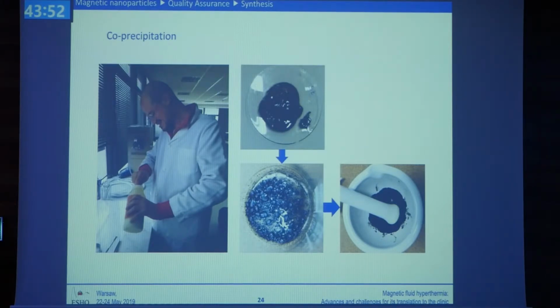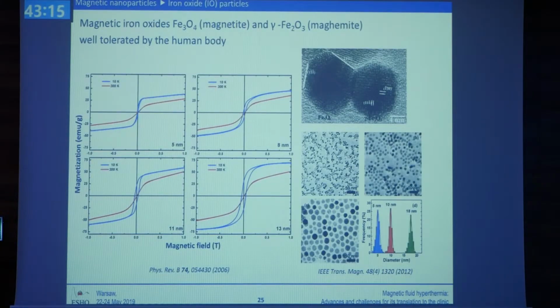You can see here how it is. This is my PhD student, Nikos, making these nanoparticles. They come out of precipitation like a slime, like black mud. Then you let it dry for a couple of days in your booth. And then you can mill it down to a real nanoparticle powder. And of course, after that, you have to put it in an aqueous solution to be dispersed. So we can create magnetite, so iron oxide nanoparticles.